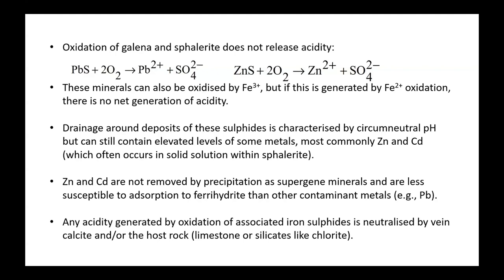However, it can contain elevated levels of some metals, most commonly zinc and cadmium. And the cadmium comes out of the sphalerite at the mine sites. Interestingly enough, although these sites are often characterized by large amounts of galena, lead isn't a big problem in the drainage because it's actually strongly adsorbed on any ferrihydrite that's around, whereas zinc and cadmium are not. And lead can also precipitate as various secondary minerals, carbonates and sulfates, whereas zinc and cadmium tend not to precipitate.